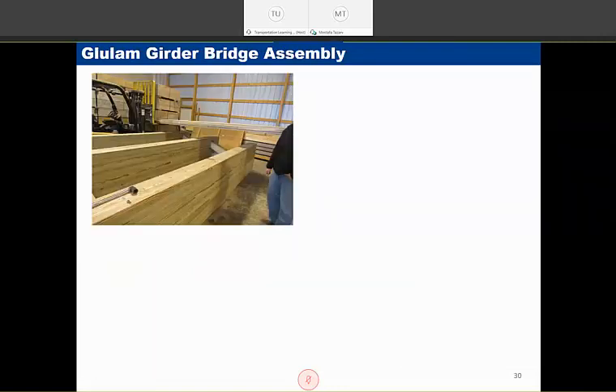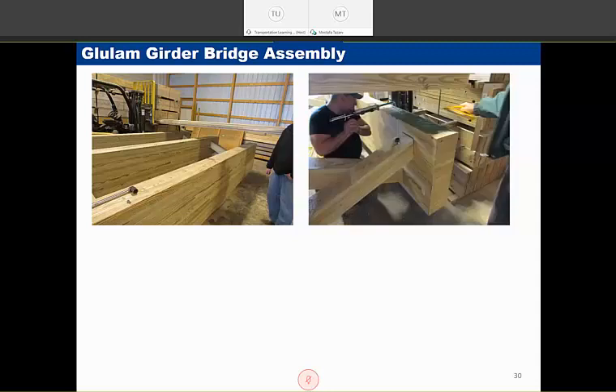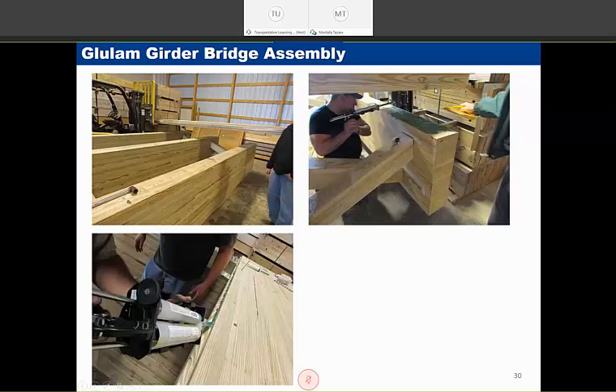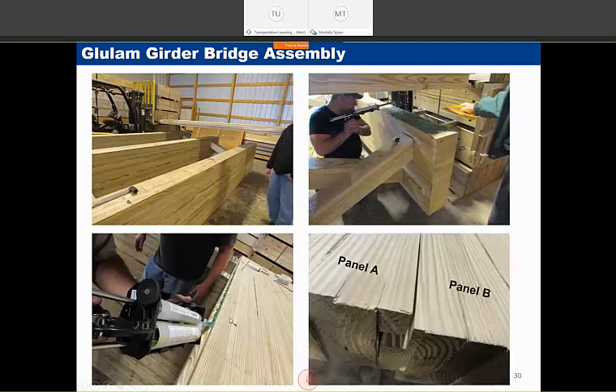So to construct the bridge, the girders were placed first, then the glulam cross braces were bolted. Subsequently, epoxy was used to connect the deck panels to girders. Also, epoxy was used for the panel-to-panel connections. So almost for all of the joints, we use epoxy for the positive and negative continuity. Here you also can see the epoxy placed between the top of the girder and bottom of the deck panel. And then here is the epoxy for panel to panel joints to finish that tongue and groove connection.